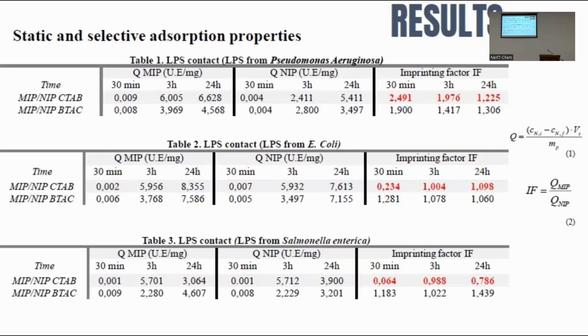Further on, it can be observed that the MIP-CTAB particles present a lower imprinting coefficient when using LPS from E. coli and Salmonella enterica, as can be seen in tables 2 and 3. Considering that the adsorption mechanism is epitope, only one portion of the entire template is involved in the formation of the specific cavities. In this case, lipid A. The imprinting factors obtained for the CTAB-based system are due to the small structural differences between the lipid A fragments from LPS from E. coli and Salmonella enterica.